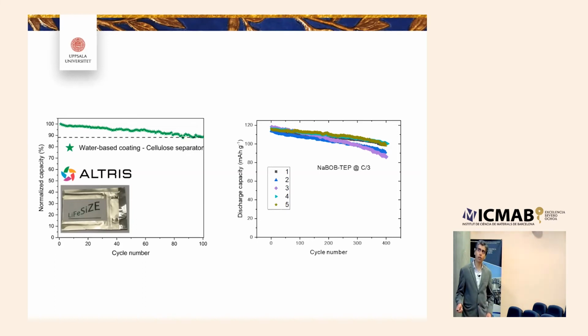On the left, you see a battery prototype based on hard carbon Prussian white, with water-based coating. Everything's water-based coating, there is no NMP here. It has a cellulose-based separator. On the right, you see 5 identical or similar cells with the electrolyte I mentioned, NaBOB in TEP.